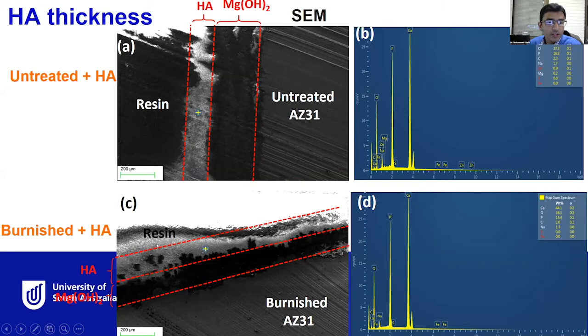One of the interesting things we can see here is that in the case of the untreated plus HA, the magnesium hydroxide layer is a little bit thicker than when you do the HA coating on a burnished surface. And we can achieve a coating thickness of around 95 micron up to 100 micron for both cases. So the HA coating is deposited pretty uniformly and quite densely, and these EDS pictures on the top and bottom confirm again the calcium and phosphate elemental presence in the cross-section of the coating.